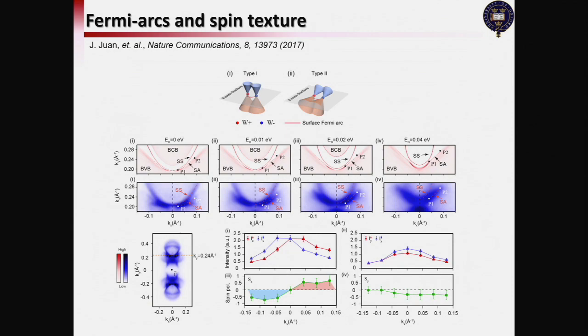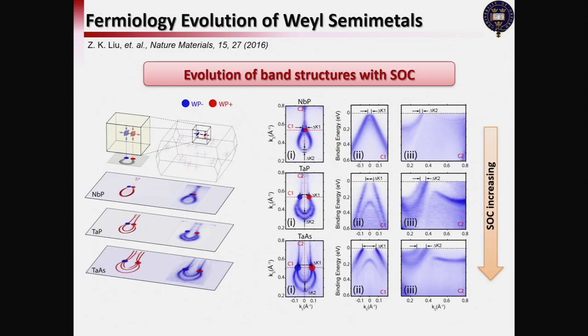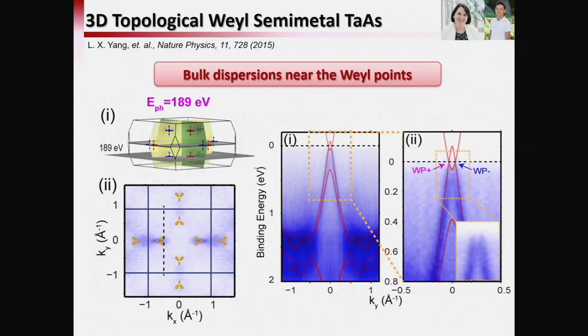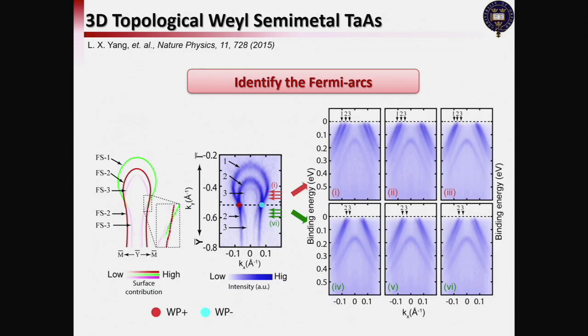The second type of topological Weyl semimetal basically tilts the Weyl cones, and then we were able to demonstrate the spin structure of the surface Fermi arcs. And this family of materials, we got from the Heusler compounds, with Claudia Felser's group.